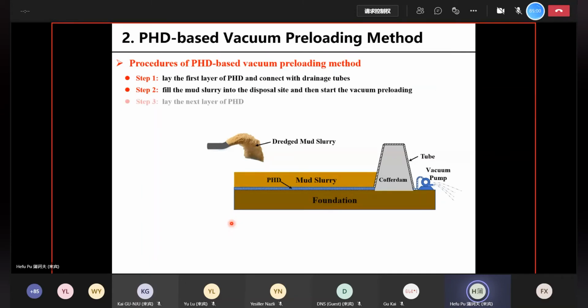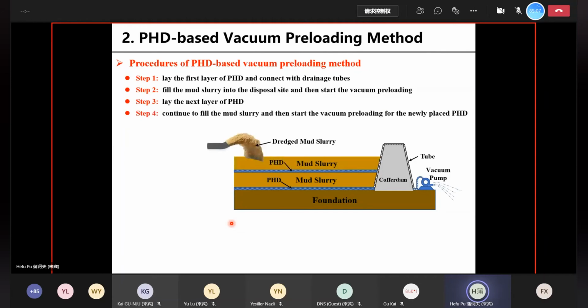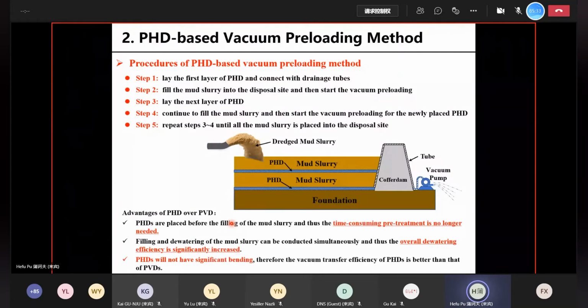slurry. And after that, we lay the next layer of PHD, and we continue to place the mud slurry into the disposal site and then start the vacuum pump to pump out water. So we repeat this process over and over again until all the mud slurry is placed into the disposal site. So conceptually, it is easy. We simply replace a vertical drain with horizontal drain, but the benefits are